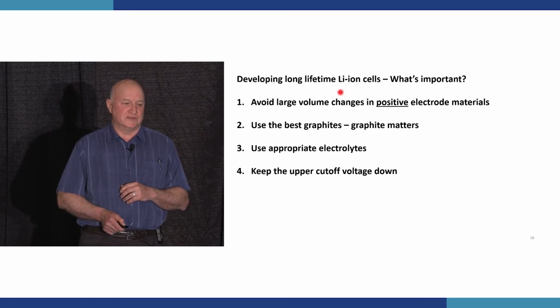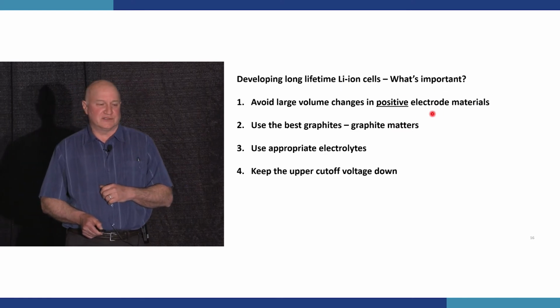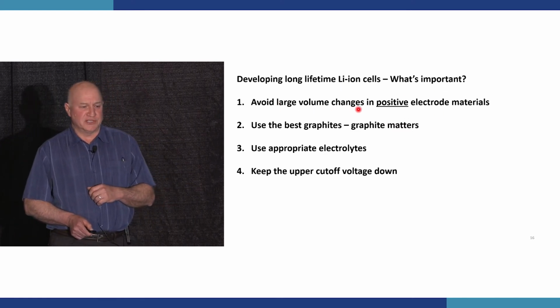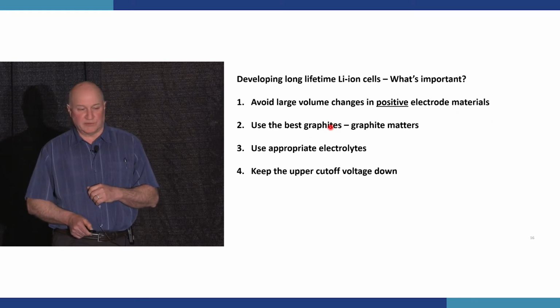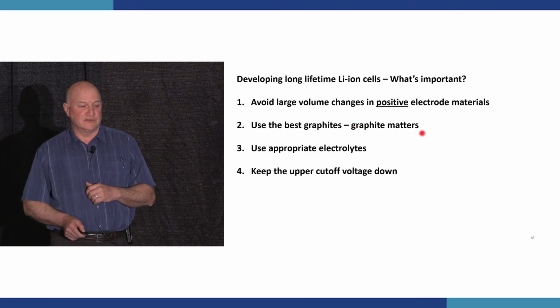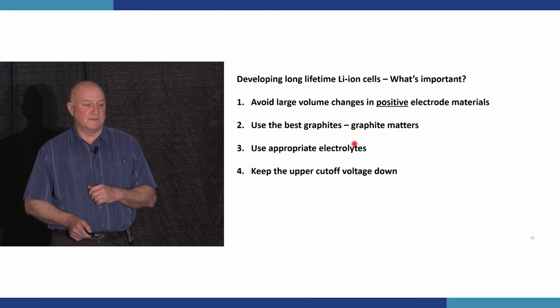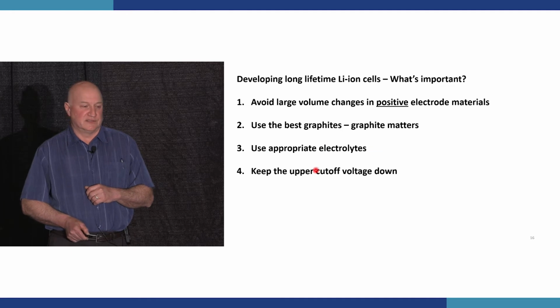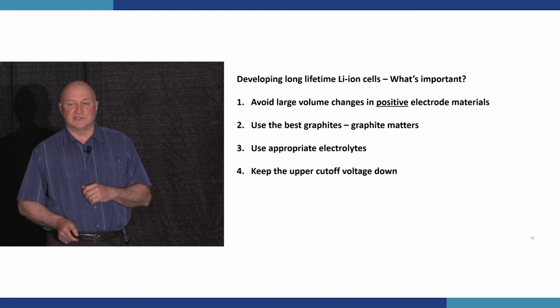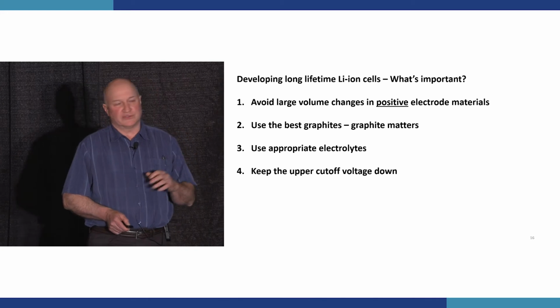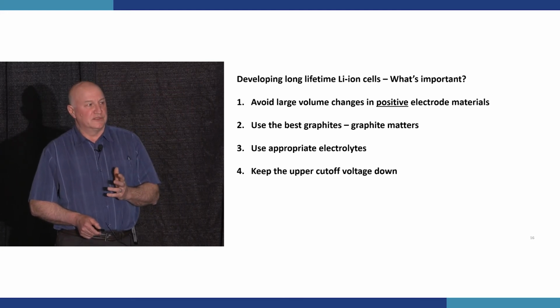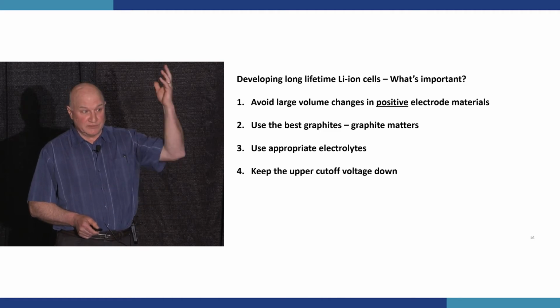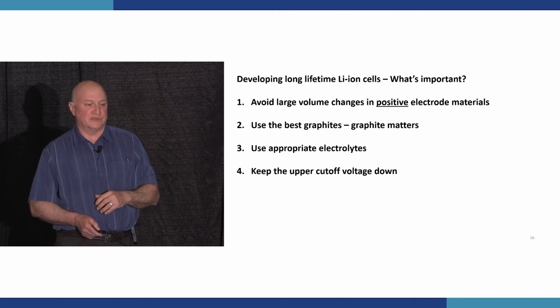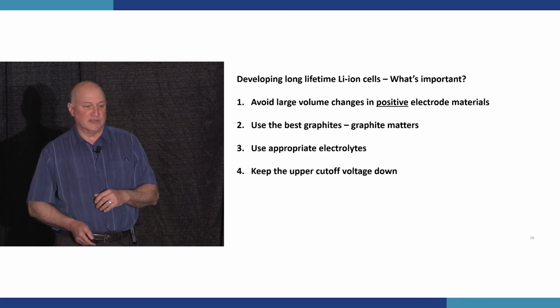So what's important for developing long lifetime lithium-ion cells? Avoid large volume changes in the positive electrode materials. I'll show you why that's important. Use the best graphites. The graphite electrode type matters a lot. Use appropriate electrolytes and keep the upper cutoff voltage down. So don't charge to very high voltages. All the electrolyte reactions with the positive electrode accelerate when the voltage is higher. So if you keep the upper voltage down, you can make a much longer lifetime cell.